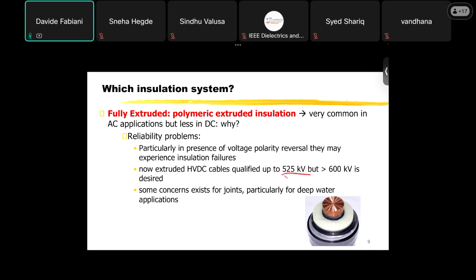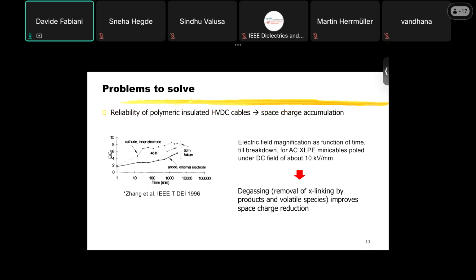But the problem is that now we want to exceed 600 kilovolt. So the reliability concern about the fact that polymeric insulation can have, of course, is still present. In particular, in joints for deep water application, the use of polymeric fully extruded insulation is still not so common due to some reliability problems. And the reliability problems that this kind of insulation has are associated with space charge accumulation.